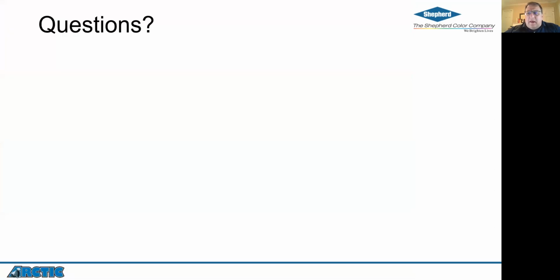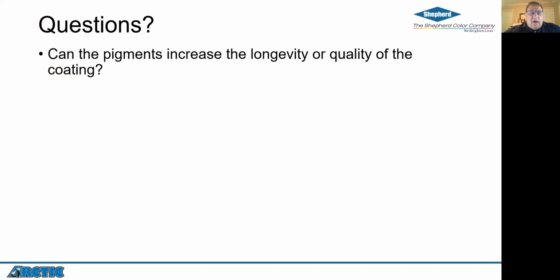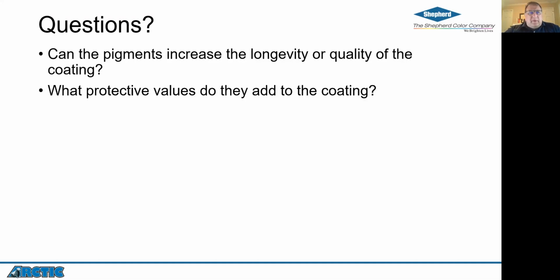We did end up getting a number of questions that I wanted to address right now. Can the pigments increase the longevity or quality of the coating? That's one thing it's hard to quantify, but what we've heard back from the marketplace is that because the materials stay cooler, and degradation is often driven by temperature, if you can keep the material cooler, it's going to degrade less. A knock-on effect is that as things heat up, they expand and contract. So the potential for materials made with IR reflective pigments is that they won't expand and contract and pull out fasteners. That is one potential benefit of using the infrared reflecting pigments.